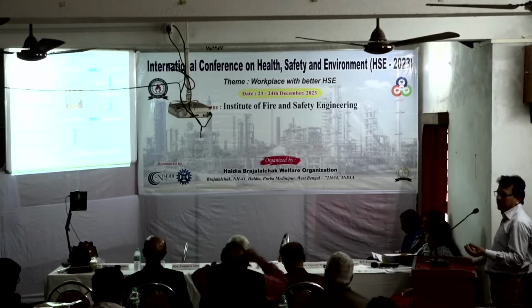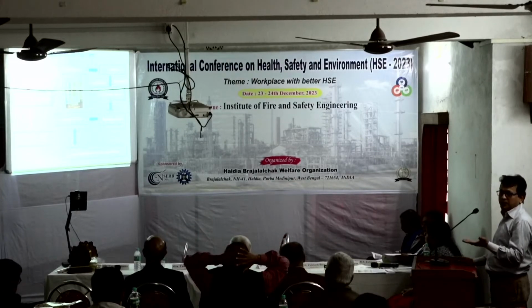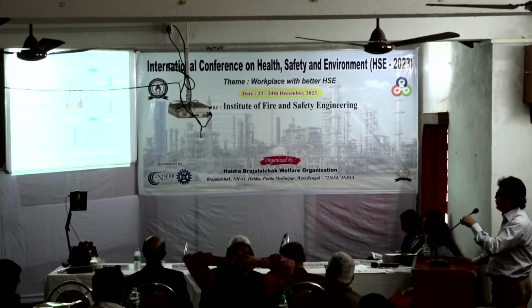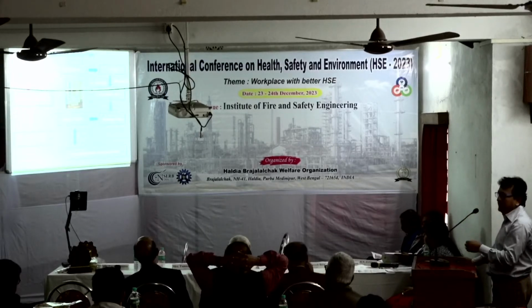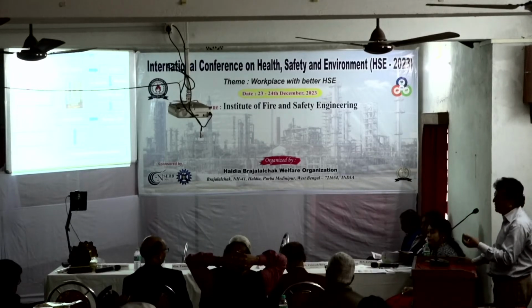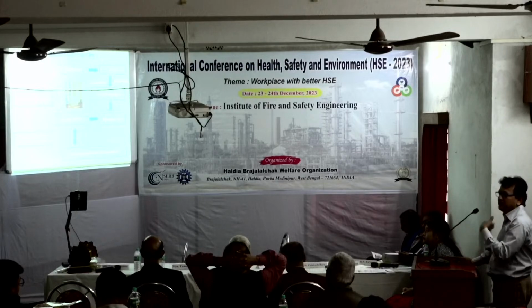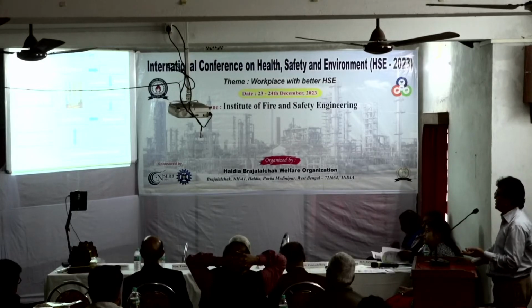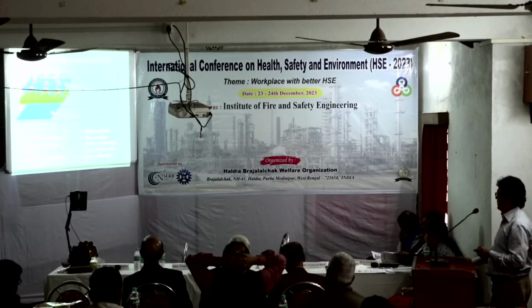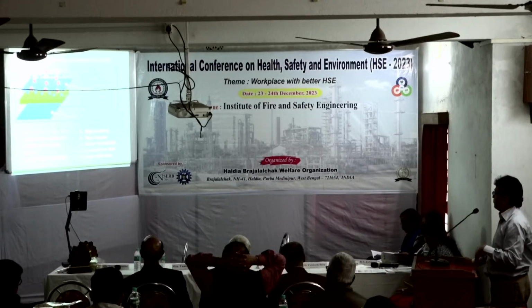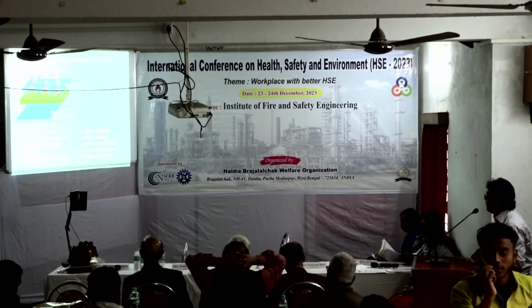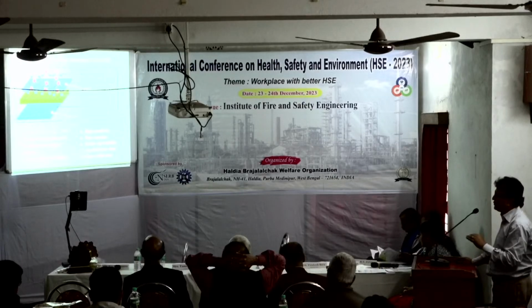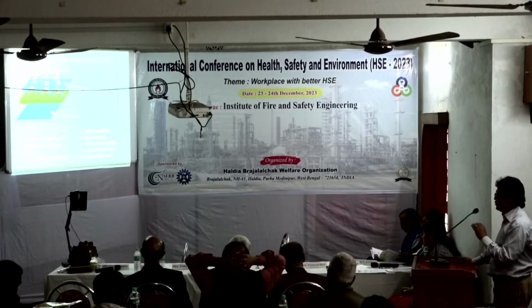The sol is prepared on one side, and the bottom electrode is prepared on the other side. Then we dip coat inside the sol, and after curing at 80 degrees centigrade, the top electrode is applied. Then the ultimate composite is fired at 900 degrees centigrade. So this is the overall proposed process, and our sensor operates up to 150 degrees centigrade, and this type of sensor is not market available. This is project based work, as an NTPC project, and the deliverables are already done.